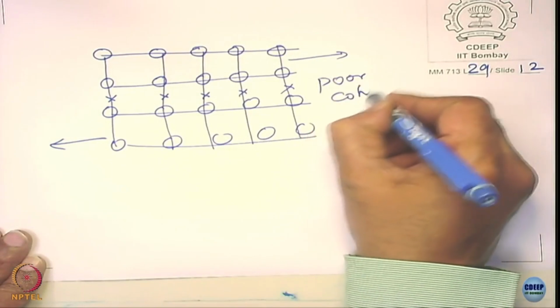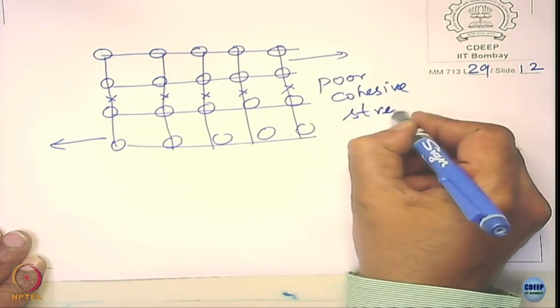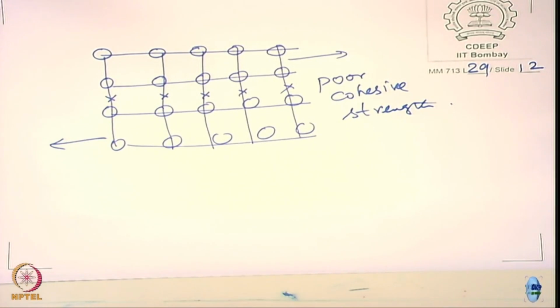This is what we call cleavage fracture. What happens in the grain boundaries is that the atoms cleave. You have one grain, another grain, and in between, the atoms just cleave out. That can happen. Of course, here corrosion can lead to that, but you also have intergranular cracking taking place in air. You talk about temper embrittlement and all these things. So they are all cleavage fractures, where the bonds between the atoms have poor cohesive strength, and it can lead to this kind of failure.